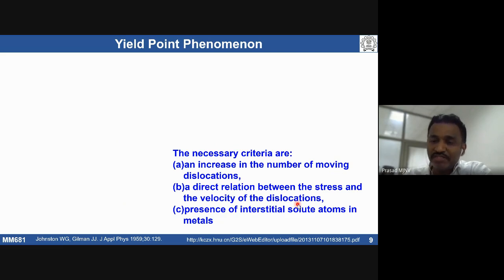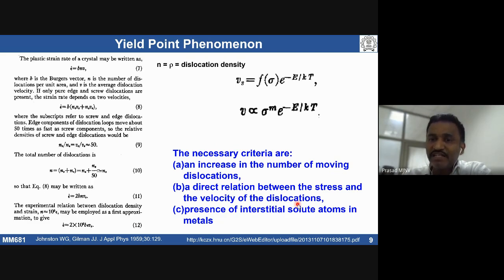So what this model said is that dislocation velocity is a function of stress and temperature. So velocity is basically proportional to sigma to the power m, where m is some exponent, and temperature is considered here.